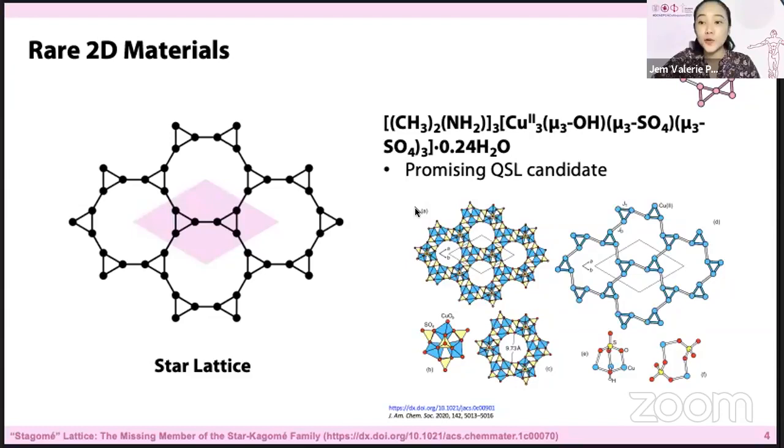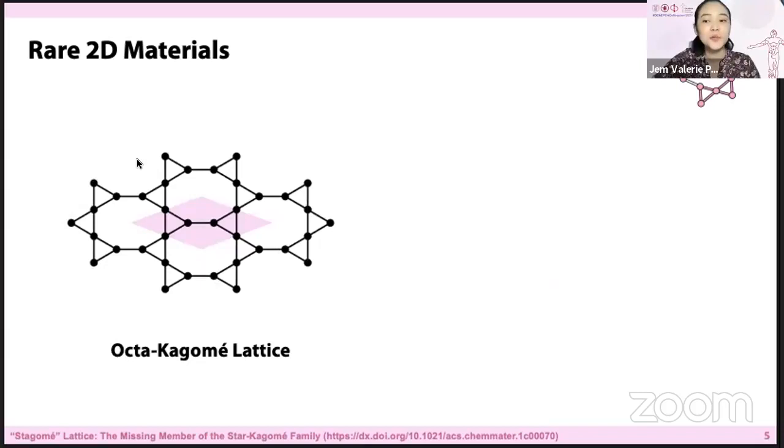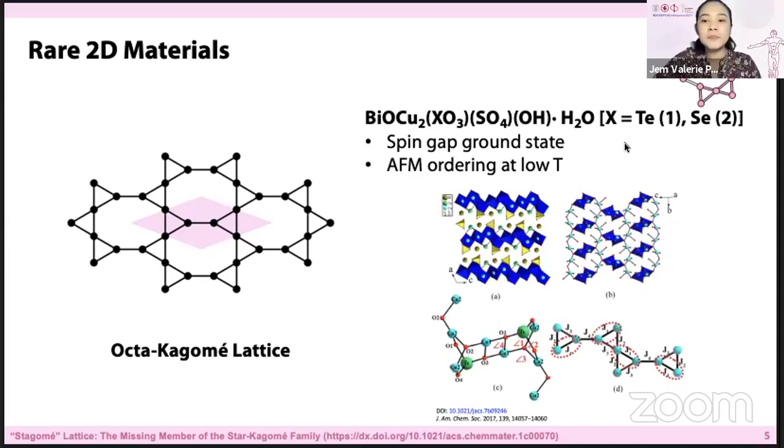And this is a previous work of Dr. Sorolla. And then also, materials with lattices intermediate between a Kagome and a star could also offer a fertile landscape for the exploration of interesting magnetic phenomena. So recently, two isostructural compounds with this rare octa-kagomé lattice have been synthesized. So one is the tellurium version. It possesses a spin gap ground state, while the selenium analog exhibits antiferromagnetic ordering at low temperatures, and both exhibit a distorted octa-kagomé